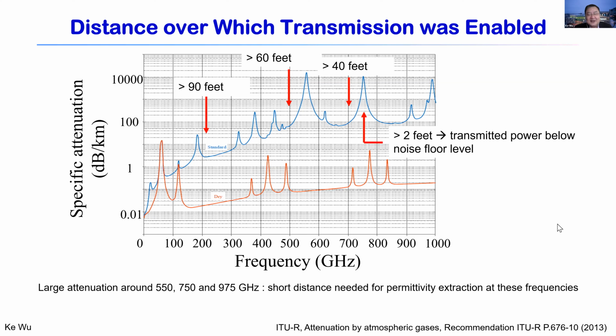If you look into this kind of spectral response, over a certain frequency range, of course, you have large attenuation naturally. So for these frequency points, the measurement should be done carefully, and even with a very short distance. You also have to be careful. Even when we talk about a few centimeters, you have to see the difference here.